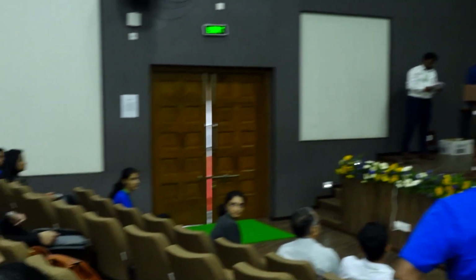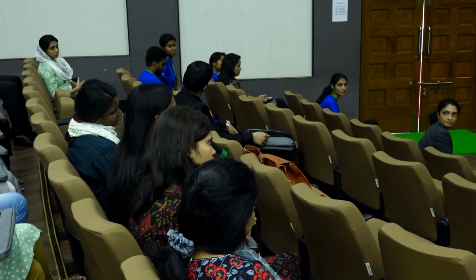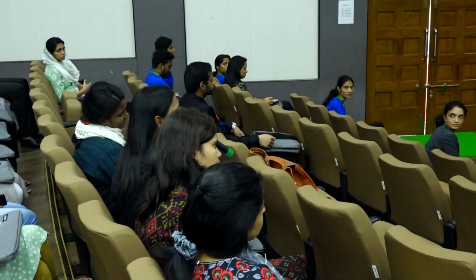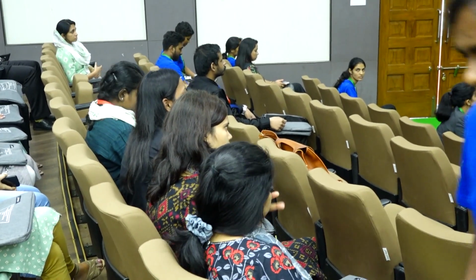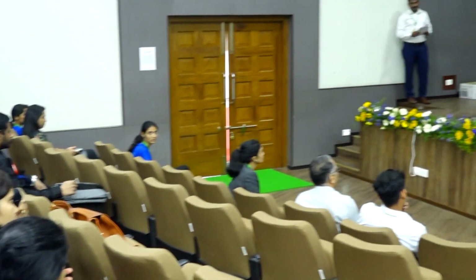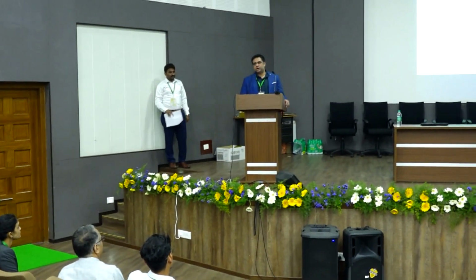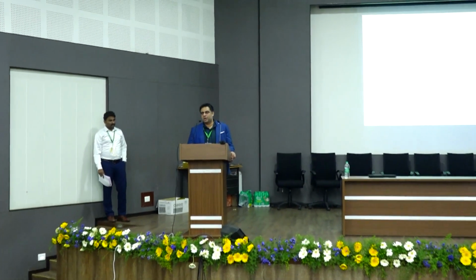Hello, sir. Can you give some light on the words activated carbon or porous carbon? Right. So if you look at non-activated carbon, you have to first understand that. Non-activated carbon is when you pyrolyze or gasify biomass, you get this char, which is black in color, and it has some porosity. And that porosity is very hierarchical. It means that there are macropores which connect to mesopores, mesopores connect to micropores, right? But often what happens is that due to tar deposition or due to non-uniform distribution of heat, some of the pore channels are not open.